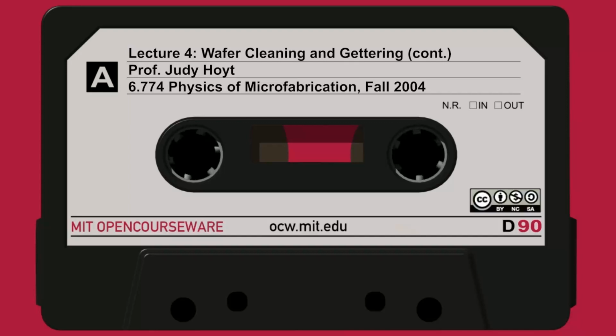Another example is iron. It's not quite as obvious. But on the right-hand side, there's a little bit more iron. It's measured here. Again, it varies from point to point because there may be some particles on this wafer, and it's picking up particles, perhaps spuriously, which contain iron. This particular spot on the wafer looks very dirty. It's got a high count, about 12 times 10 to the 10th.